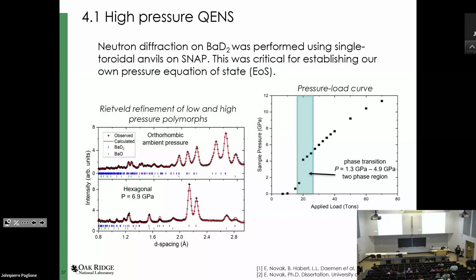but then you really need to use diffraction to measure the actual pressure based on your sample. And I think Adam will also talk about diffraction standards and things like that later, so you'll hear more about equations of state then. When we started with this project, we first made a deuterated version, which we measured on our high pressure diffractometer to understand the high pressure behavior. We noticed that because this sample has to be loaded without a pressure medium to avoid any unwanted reactions, there is quite a large regime where you have coexistence of both these phases. So for the QENS experiments, we had to be careful that we get to a high enough pressure, which is actually higher than what we saw from all these previous works, to make sure that we actually probe just the high pressure polymorph.